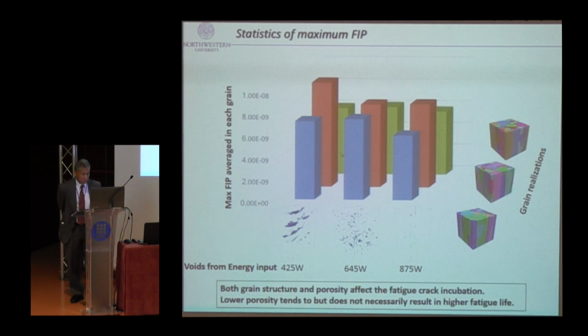And both grain structure and porosity affect the fatigue crack incubation. Sometimes people believe that lower porosity tends to, but does not necessarily result in higher fatigue life. So the key thing is it depends on loading direction, but it's a very complex loading direction because of the crystal plasticity, crystal orientations, and with void, there are only 2 parameters we are looking at, but those are 2 key parameters we are looking at.